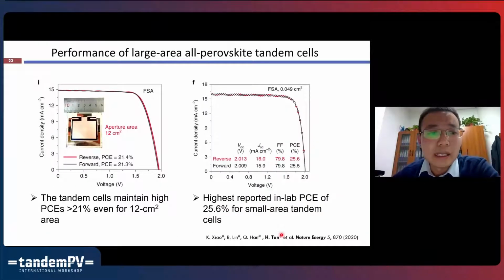We also tried to make larger area tandem devices, going beyond around 12 centimeters square for the aperture area, and it can still maintain a good efficiency higher than 21%. And we also tried smaller area tandem devices, and due to the passivation ability of this molecule, it can give us a higher efficiency than we could get previously. The best efficiency we measured in lab is 25.6%, but this is not a certified value.